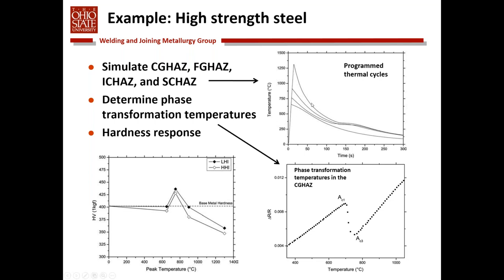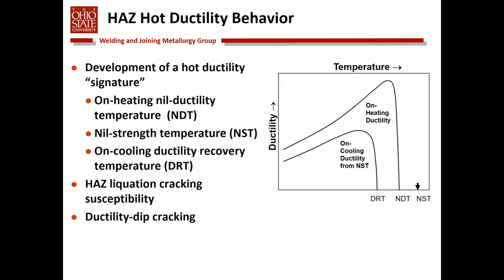And based on samples that are generated or cooling rates, we can look at phase transformation temperatures in terms of the A1 and the A3 temperature. We can generate samples and then look at, for example, hardness behavior. In this particular steel, we actually get a softening phenomena in the heat affected zone relative to the base metal hardness. And so the Gleeble has the opportunity and the ability to provide a lot of data regarding what happens in the heat affected zone.